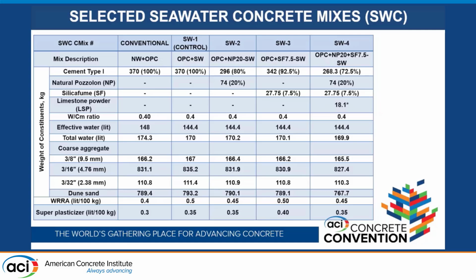And there you see the details of the mixes which were used. Typically, the Saudi Aramco mix has 370 kilograms per meter cube of cement that was fixed, and the water cement ratio was generally kept constant at 0.4. And other than that, we have the coarse aggregates, which are natural coarse aggregate, and dune sand was used in most of the formulations.